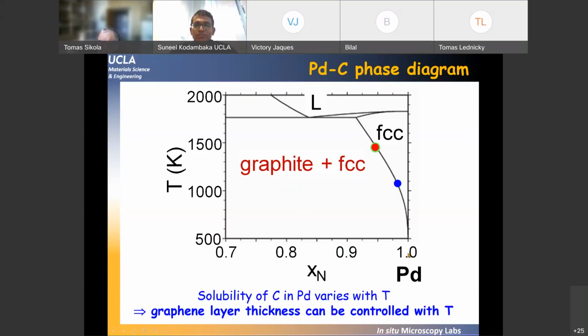This is a partial phase diagram of carbon-palladium. On the palladium-rich side, what you see here is that palladium can dissolve carbon and exist in the face-centered cubic structure at high temperatures. But as you cool down, you have graphite formation. You have a two-phase region, which is palladium with a little bit of carbon in the FCC lattice, and graphite. Now, depending on the temperature to which you heat and cool, the amount of graphite you precipitate also changes. So we take advantage of this process to first form a solid solution that exists as a face-centered cubic crystal of palladium and carbon. And as we cool it down, we cool it to the right temperature where we obtain either a monolayer or a bilayer or multilayer graphene.